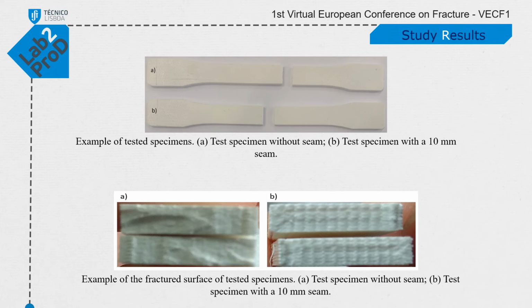Here we show two broken specimens after the tensile test. From the fractured surface, it is possible to observe that specimens with seams display a smoother surface than specimens without them, and that the fracture location is always in one of the ends of the seam when there is one.